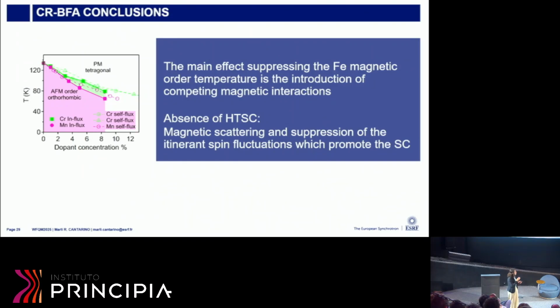Trying to understand everything we saw for this phase diagram, the absence of high temperature superconductivity should be because of the magnetic scattering and suppression of the itinerant spin fluctuations, which would promote the superconductivity.